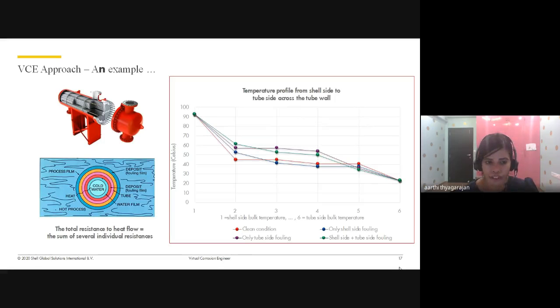Only 5% of our heat exchangers are inspected. Based on the modeling, we calculated at an hourly rate the exceedance beyond the limiting skin temperature for each of these exchangers, and hence we calculated the cumulative value and correlated that with the inspection data. Now let's say 5% of the asset was inspected. Based on the correlation, you can actually calculate the actual corrosion rate for the 95% of the other heat exchangers, which is otherwise called unknown.